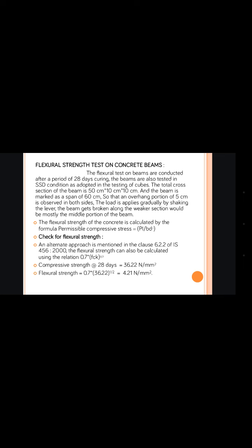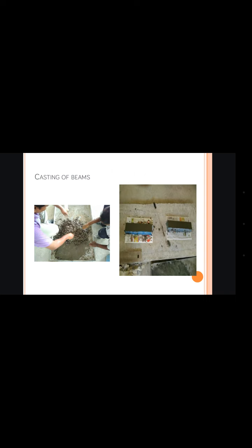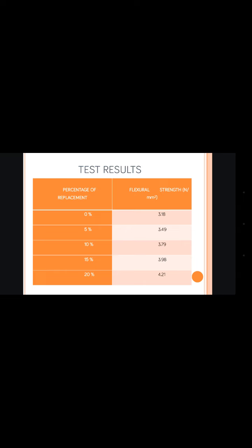Now the next test which we carried out is flexural strength on concrete beams, prisms. An alternate approach is mentioned in clause 6.2.2 of IS 456-2000, that the flexural strength can also be calculated using the relation 0.7 times root fck. So these are the prism castings. Test results: even in this, we can find that as we increase the percentage of e-waste incorporation, the flexural strength also increases.